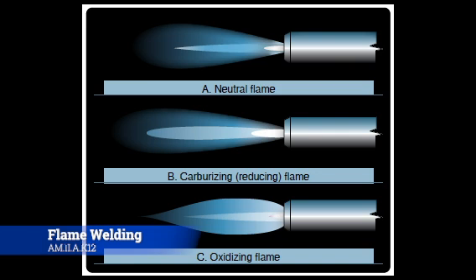The oxidizing flame burns at approximately 6,300 degrees Fahrenheit and is produced by burning an excess of oxygen. It takes about 2 parts of oxygen to 1 part of acetylene to produce this flame. It can be identified by the shorter outer flame and by the small white inner core. To attain this flame, start with a neutral flame and then open the oxygen valve until the inner cone is about 1/10 of its original length. The oxidizing flame makes a hissing sound, and the inner cone is somewhat pointed and has a purplish color at the tip. The oxidizing flame has some specific uses. A slightly oxidizing flame is used for bronze welding, like brazing of steel and cast iron. A stronger oxidizing flame is used for fusion welding of brass and bronze, and if an oxidizing flame is used on steel, it causes the molten metal to foam, give off sparks, and burn.